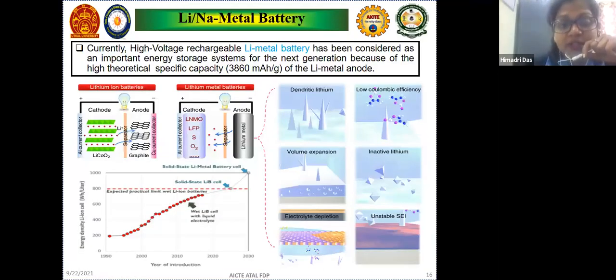Apart from that, I have already said that lithium metal ion batteries are very beneficial like other metal ion batteries. So people have started focusing on lithium metal batteries. What is the real advantage of using lithium metal as anode? Usually in a half cell we use this lithium metal. There we have found that the capacity is very high, and when we actually make a full cell, the capacity of the full cell reduces because of the specific mass. So to improve that specific capacity, people have used only the metal, like lithium metal. And one interesting fact is that when you use a lithium metal battery, the amount of lithium will be sufficient compared to a lithium ion battery, because from the lithium itself we can get the lithium ions, and there will be no insufficiency of lithium metal.